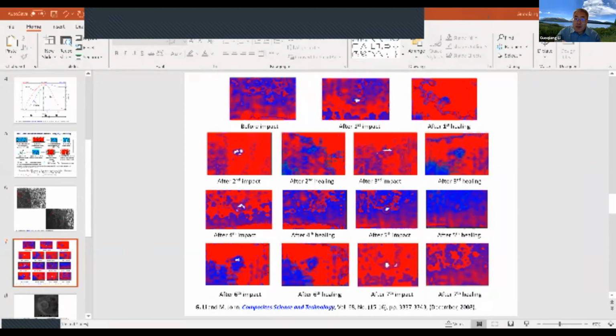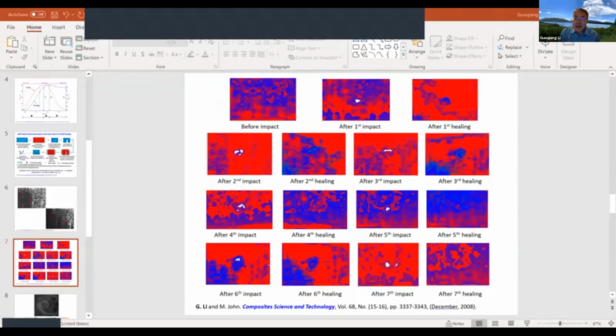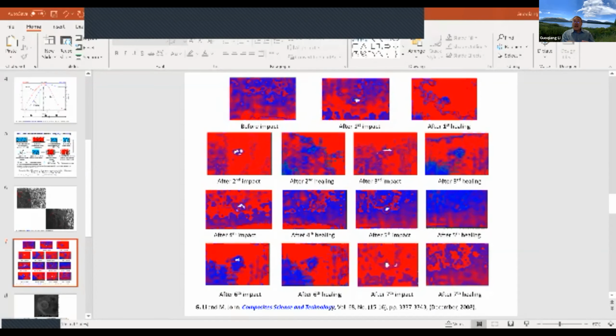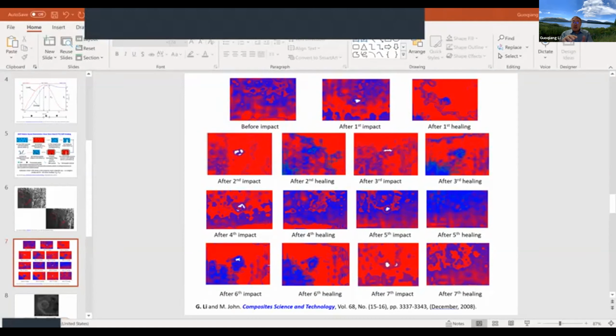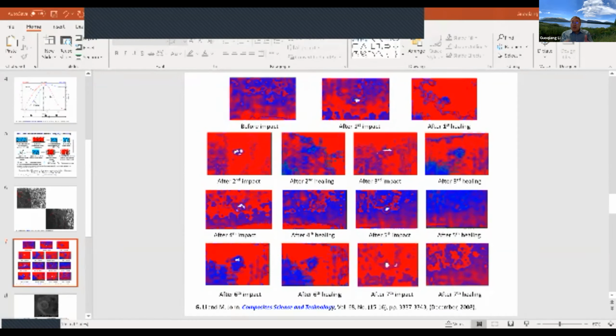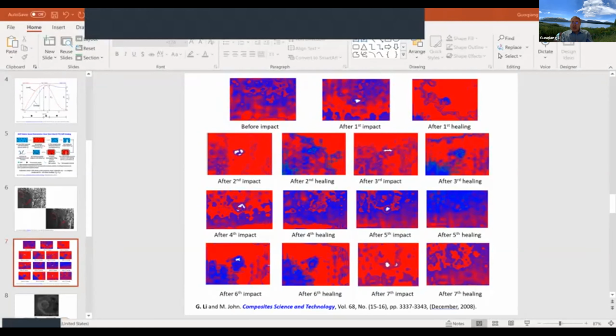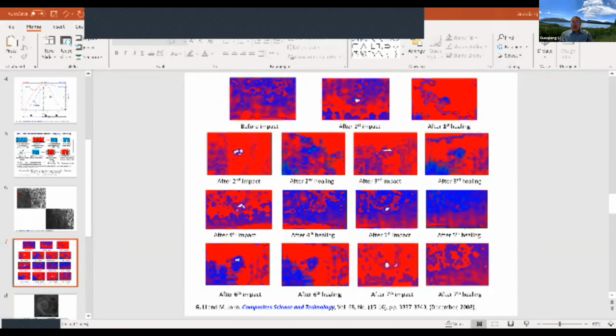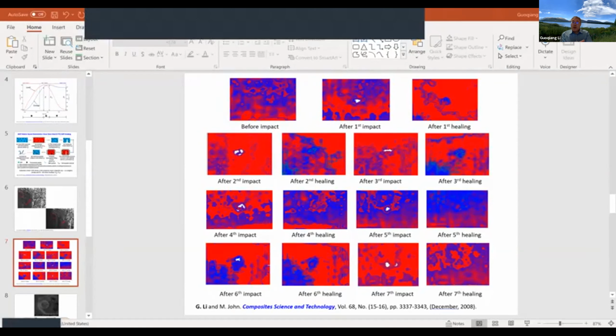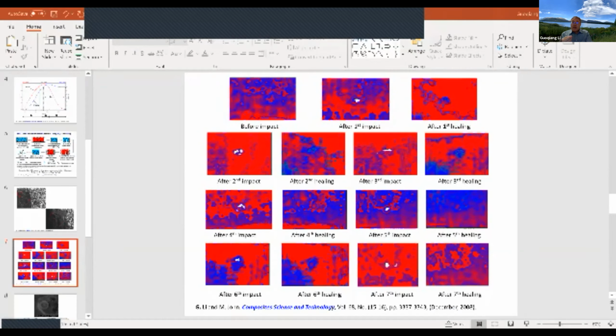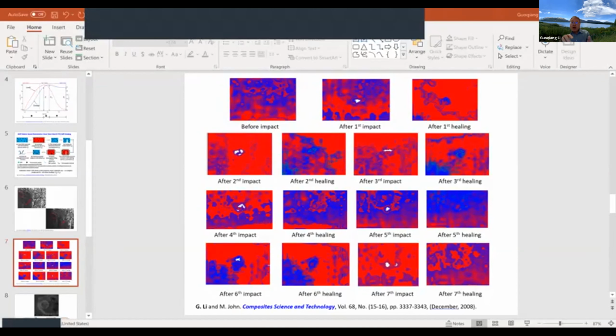Okay, so you may wonder why the color changes during the process, right? During different times, because each time you have the damage and you also have the heating process. That means you heat it up. So the material may adjust its microstructures, and even the signal we use may not be the same each time. For example, we put the sample in the water bath, right? Even the distance from the surface, all this may change the color. But what's important here is a white spot. That is an impact damage, and after heating, basically that spot disappears.